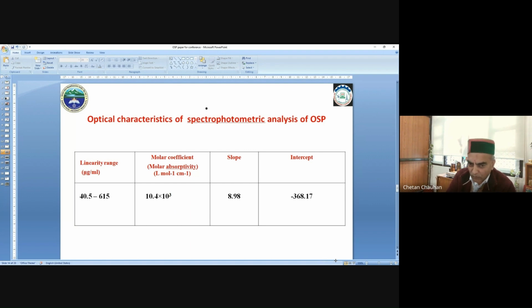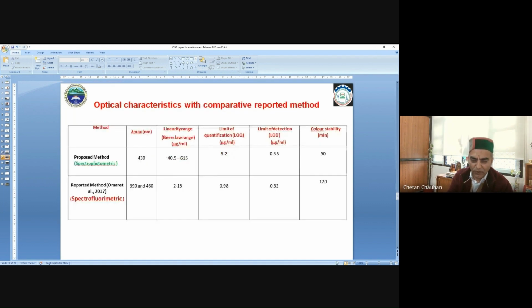Similarly, the molar absorptivity coefficient for this reaction is higher, that is 10.4 into 10 raised to power 3. If we look into the other optical characteristics and the comparative aspect with some other superior method, it has been found that it is comparable even with the superior spectrophotometric method which has been reported in the literature. Being a cost-effective method, we can have a better limit of detection and limit of quantification by exploring this method. Although the other superior method has a little bit higher color stability, we have color stability up to 90 minutes. That is more than sufficient for the time which can be consumed for the measurement.